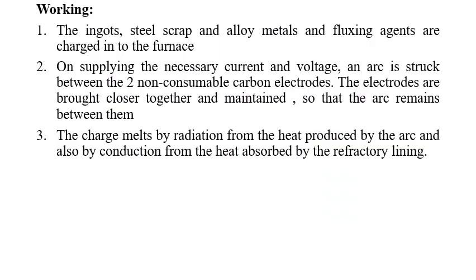Next, the ingots, steel scrap, alloy metals and fluxing agent are charged into the furnace. On supplying the necessary current and voltage, an arc is struck between the two non-consumable carbon electrodes. The electrodes are brought closer together and maintained so that the arc remains between them. Third important point, the charge melts by radiation from the heat produced by the arc and also by conduction from the heat absorbed by the refractory lining.